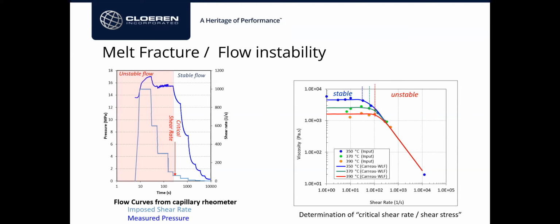Okay. What is the best point to modify rheology? Changing the temperature in the extruder or in the die? To modify the rheology, you have many ways, but the impact of die temperature is usually fairly low because of the relatively short residence time, typically, and the polymer thermal conductivity being fairly low. There's not enough flow length or time for the material to be either cooled or heated up. There's some slight impact, but it's not typically enough, right? And setting melt temperature is definitely a more efficient way.